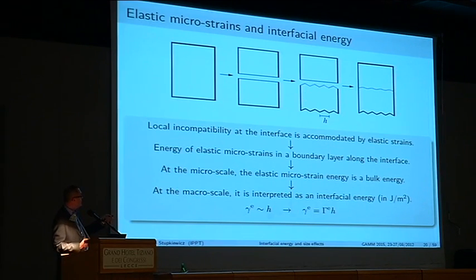Of course, the material will be intact far away from the interface, but locally you need some elastic strains to accommodate the incompatibility. So this local incompatibility is accommodated by the elastic strains here. This, I think, is easily imagined. So along the interface, we have a boundary layer, a transition layer with elastic strains, which means with elastic strain energy. At the micro scale, this is the bulk energy, which is distributed in the vicinity of the interface. But if we integrate and look from far away, from the macroscopic point of view, this is an interfacial energy, which means a density of energy per unit area of this macroscopic or nominal interface. And what can also be shown is that this energy is proportional to the spacing here.